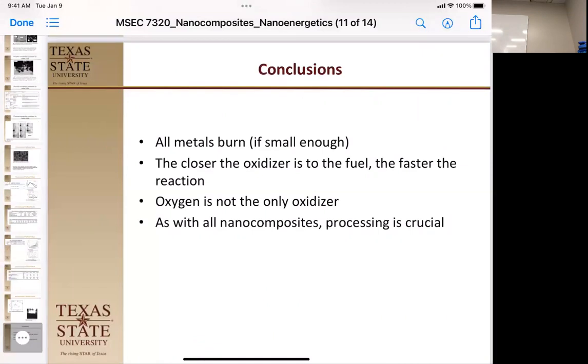Oxygen is not our only oxidizer. Now, in most propellants here, you have ammonium nitrate or something like that. Oxygen is still the oxidizer. But in the case of the fluorine system or the Teflon and Viton system, we have fluorine as our oxidizer. Those are actually two of the best oxidizers out there. If you look at where they are in the periodic table, chlorine's okay too, but fluorine's better.